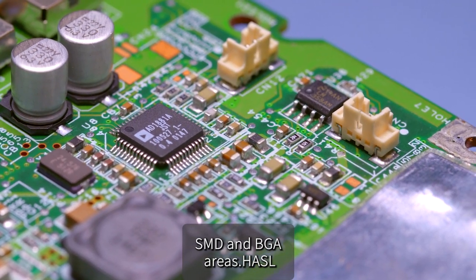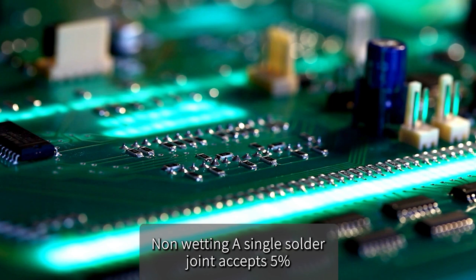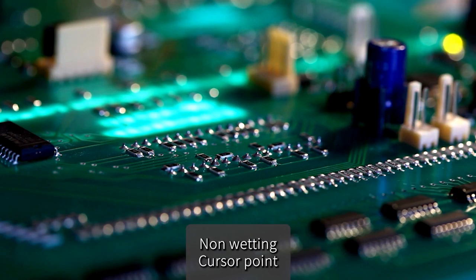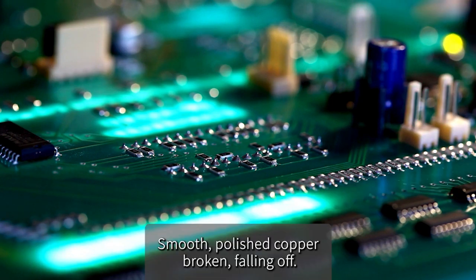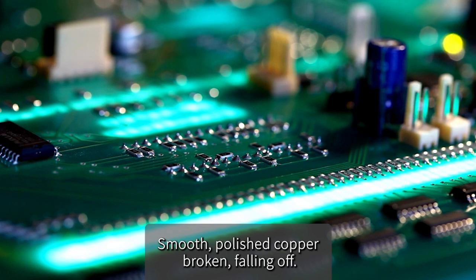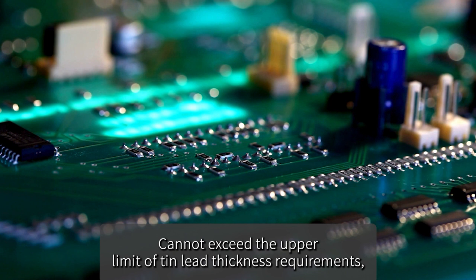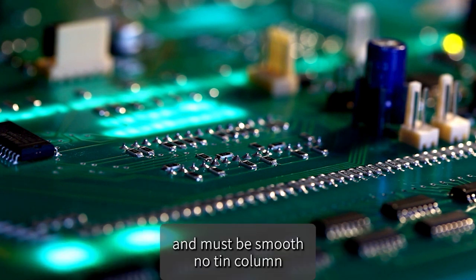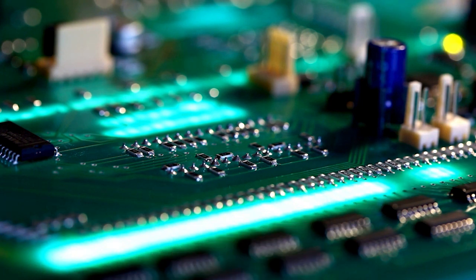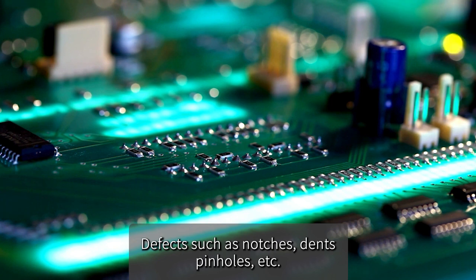Non-wetting. A single solder joint accepts 5% non-wetting. Smooth, polished copper must not be broken or falling off. The tin-lead thickness cannot exceed the upper limit of the requirements, and must be smooth, with no tin column. Defects such as notches, dents, pinholes, etc.